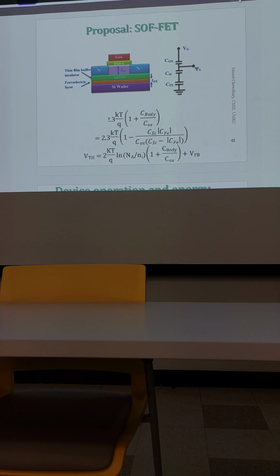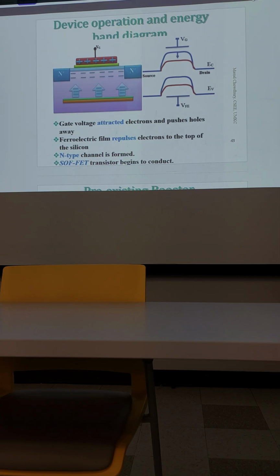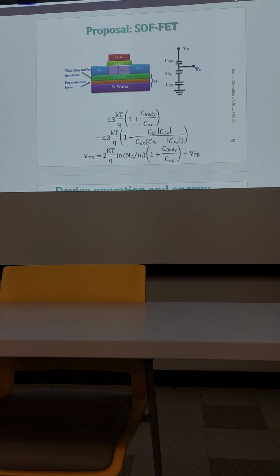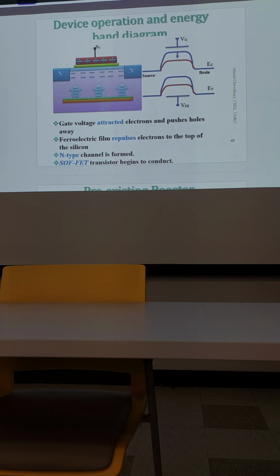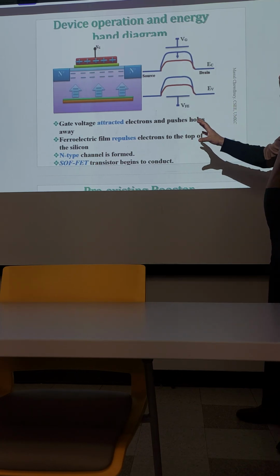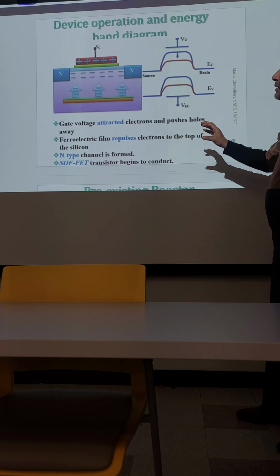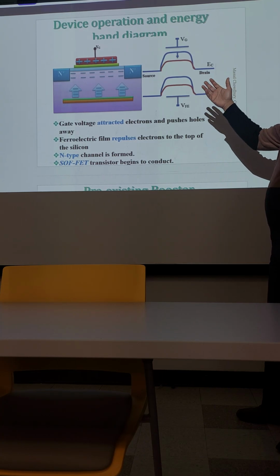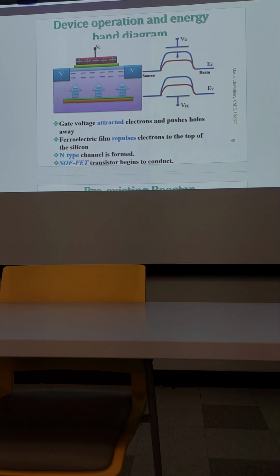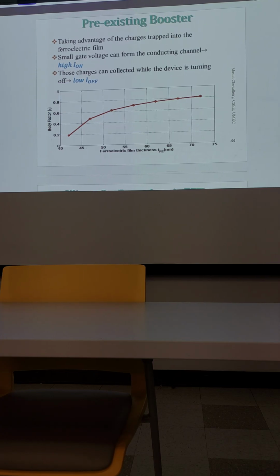So with that design modification, it is still theoretical. Nobody can give us a prototype of this device. So the analysis is purely computational, based on device modeling. And theoretically, based on simulation, we proved that a negative capacitance can be achieved, and less than 60 millivolt per decade can be achieved. So the operation of this proposed device, we call it SOFFET, silicon on ferroelectric insulator field effect transistor, is very similar to an SOI device. So this is basically what we found.